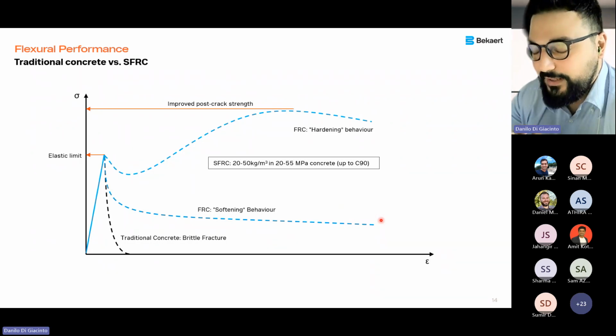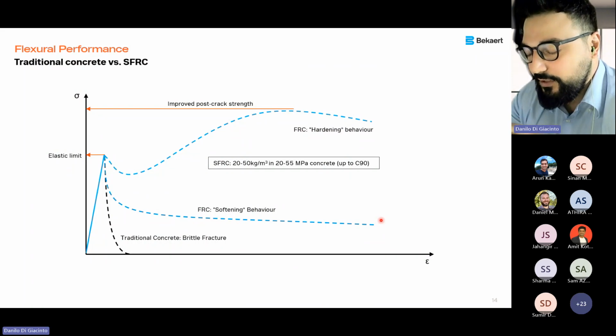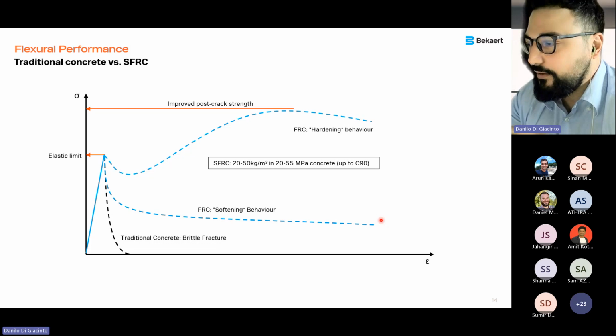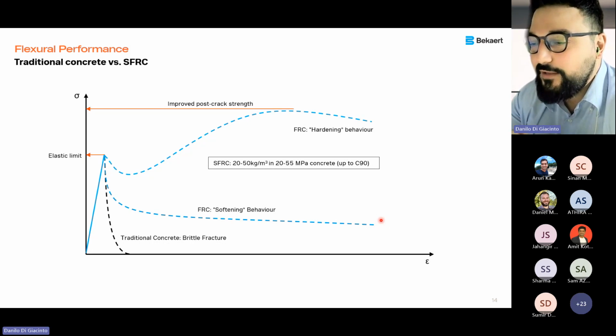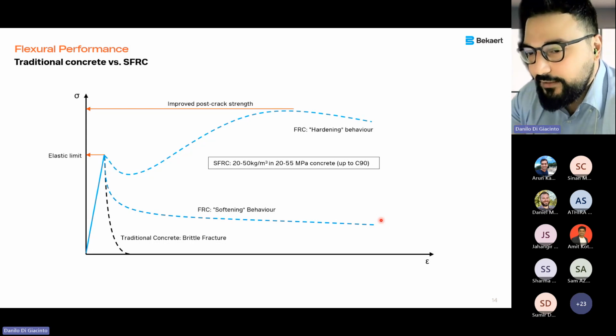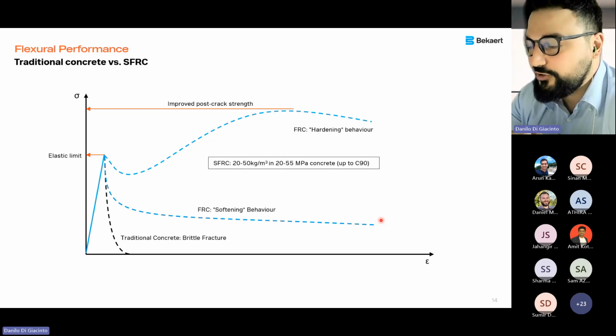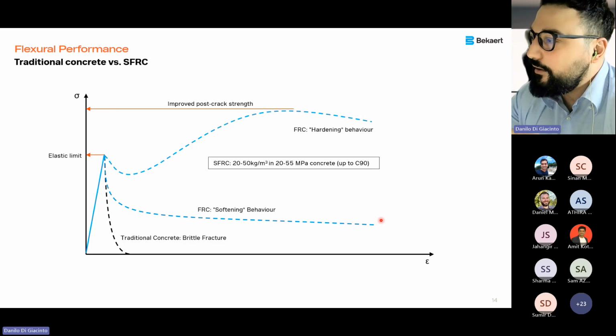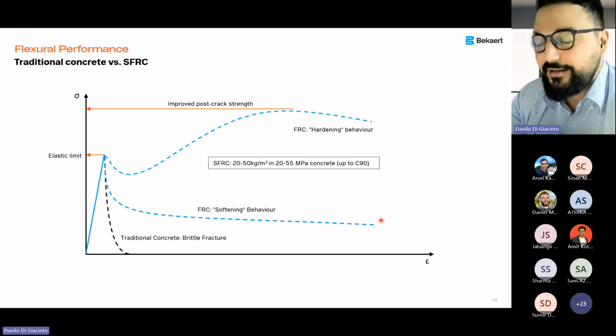What is a softening behavior? It is basically when you reach the cracking strength, your structure cracks, and you cannot achieve a higher load, but you have a ductile structure. So the collapse is not brittle as in plain concrete. When you have a hardening behavior, you can even achieve a load which is higher than the cracking load. So after the cracking, you have controlled cracking in your structure. Fibers can bridge cracks, new cracks, early cracks, and there is an improvement of the post-cracking.